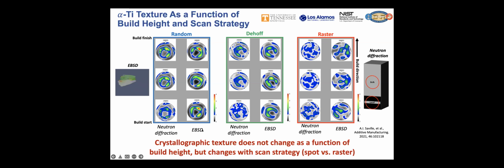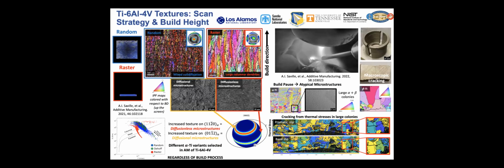We also then compared this to large scale electron backscatter diffraction that we did in collaboration with NIST here in Colorado up in Boulder. So there's a lot going on this slide. I'm just going to highlight some important points. I'm going to use the bounding condition of our random spot melt scan strategy and our raster. And what we can do is we can look at the as-built microstructure. We can then apply the orientation relationship and back calculate the high temperature beta microstructure as shown above here. So here we have the beta microstructural condition for the random spot melt scan strategy and the raster scan strategy.